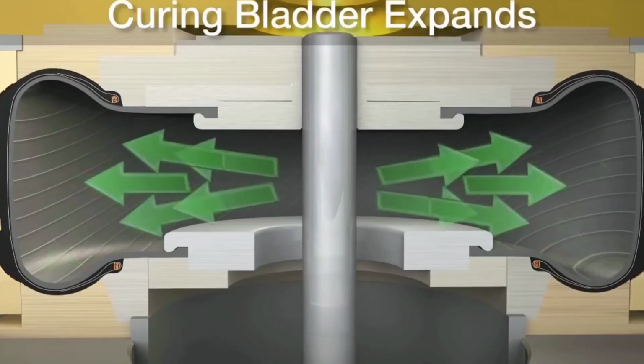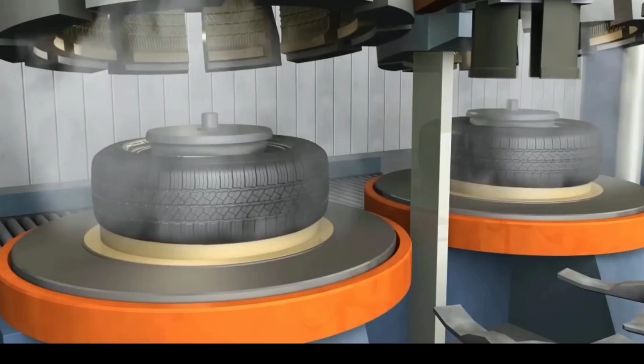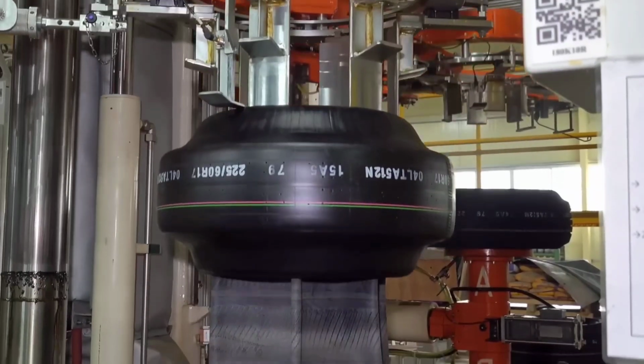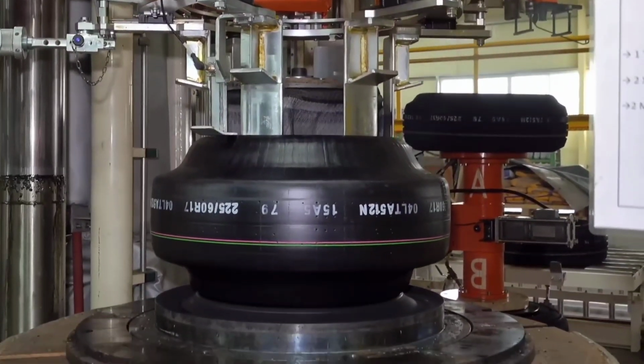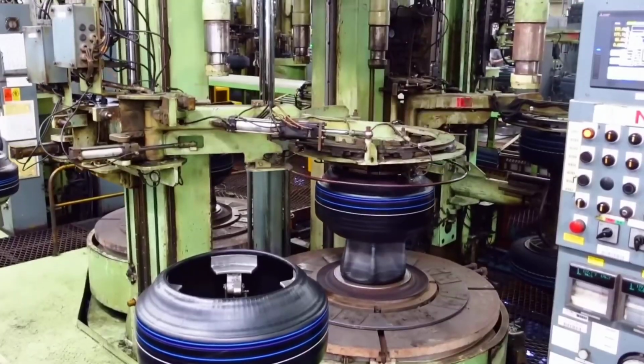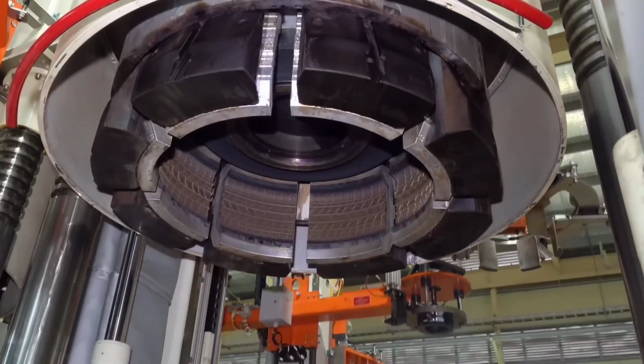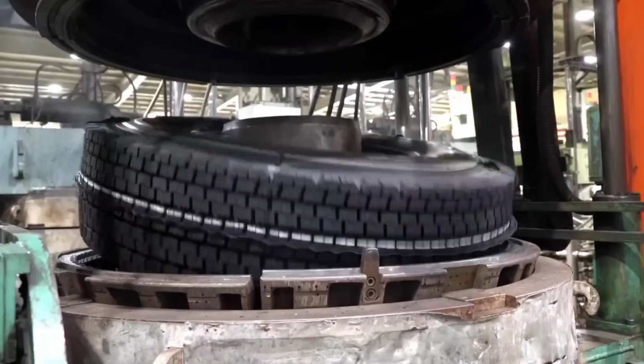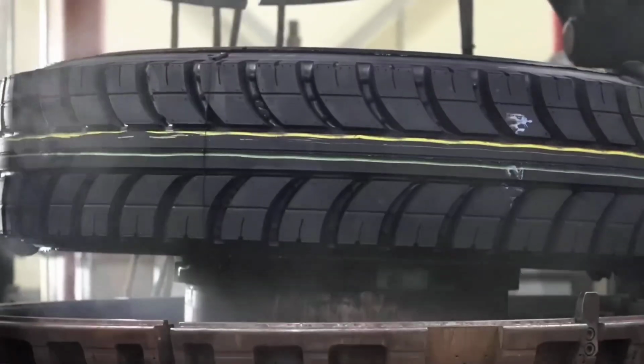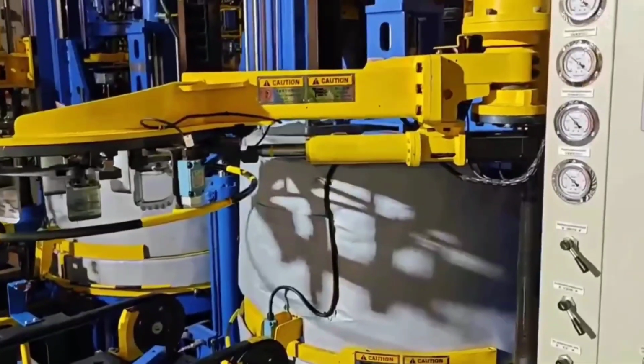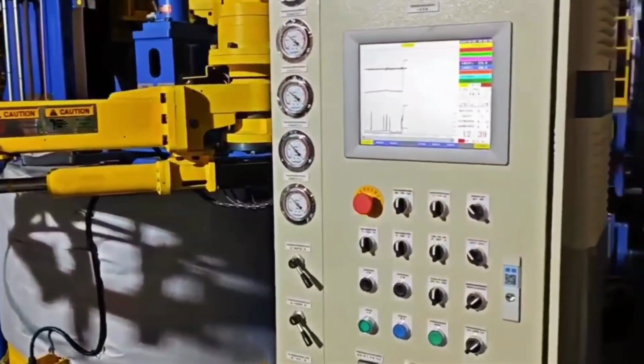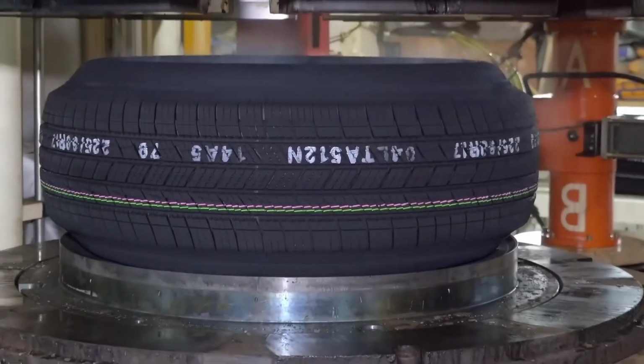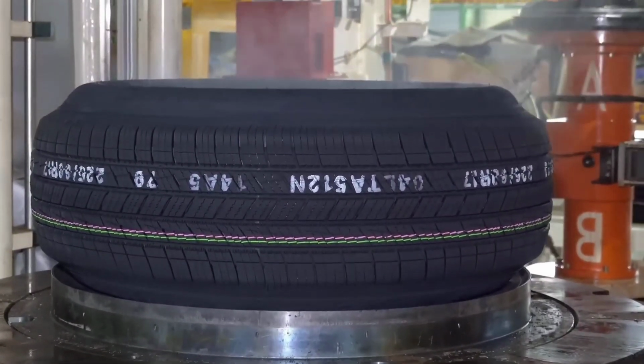However, in larger and more advanced factories, the tread is formed directly during vulcanization, a process that's both more precise and cost-efficient. The entire tire assembly is placed into a two-piece metal mold, sealed tightly like a giant waffle iron. Inside the mold, intricate negative patterns define the exact design of the tread. Once the cycle begins, the system heats the mold to around 160 to 180 degrees.